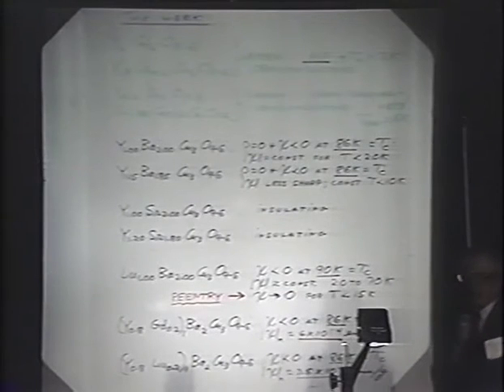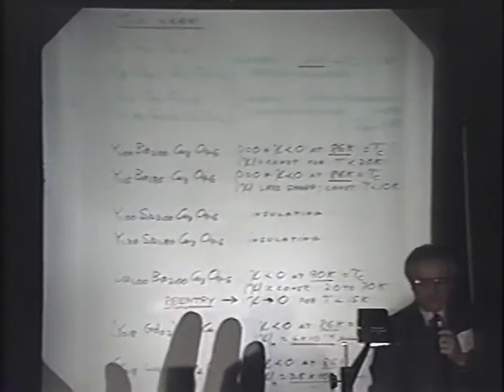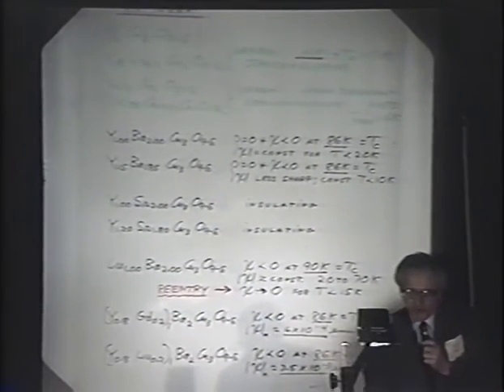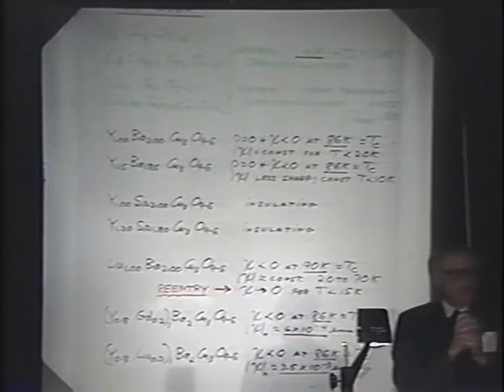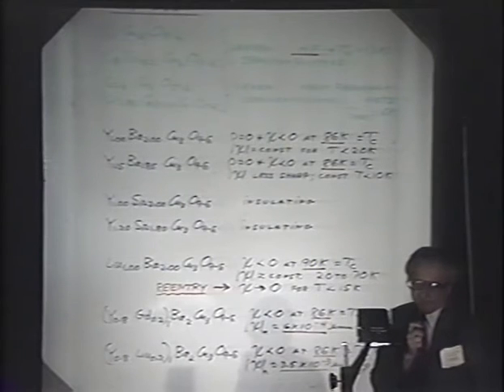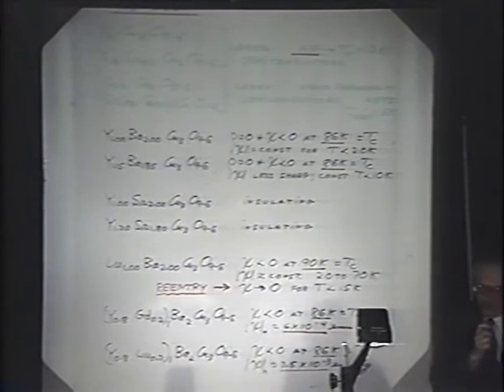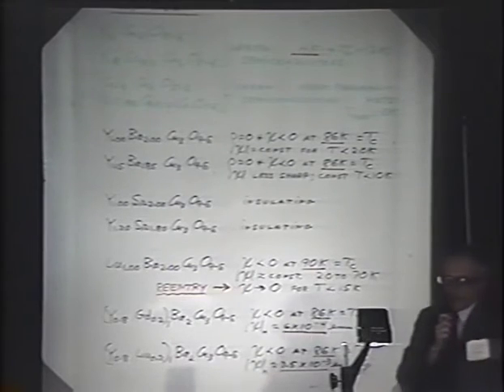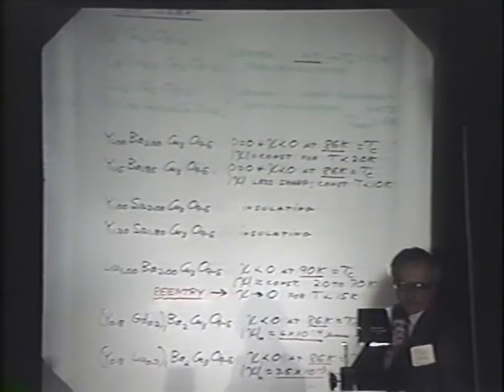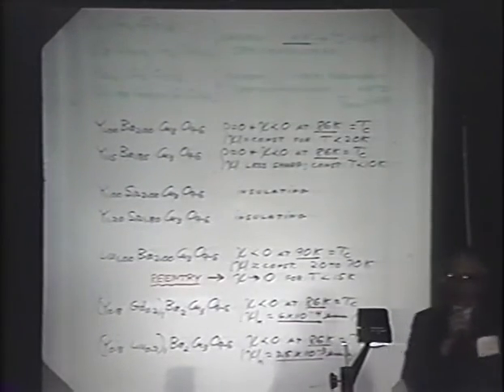Well, then our final efforts, which just have very recently begun, perhaps even they are still going on now, since it is morning in Holland, or late morning. To summarize what has been happening this week, the green phase we tried to duplicate. I think it's not the proper green phase, but what we ran into here was antiferromagnetism and semiconducting behavior. We then went on to reproduce the 1, 2, 3 phase. We've been getting temperatures around 86 degrees. We haven't yet optimized the heat treatments to get higher temperatures. We did a 1, 2 strontium phase with copper 3 and varied it a little bit. This turned out to be an insulating phase.